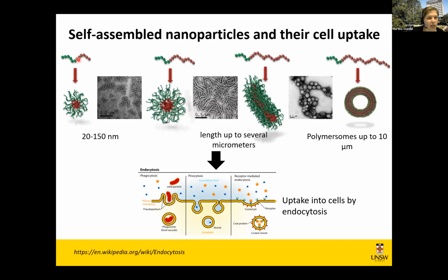By changing that hydrophobic block, we might start off with very small micelles. We make that hydrophobic block a little bit bigger, we might get bigger micelles. Now if we make it even longer, we start getting nanoparticles that are non-spherical. These are cylindrical micelles, and this is a transmission electron microscope picture of these cylindrical micelles. And if we make it a little bit longer, we get something like polymersomes.